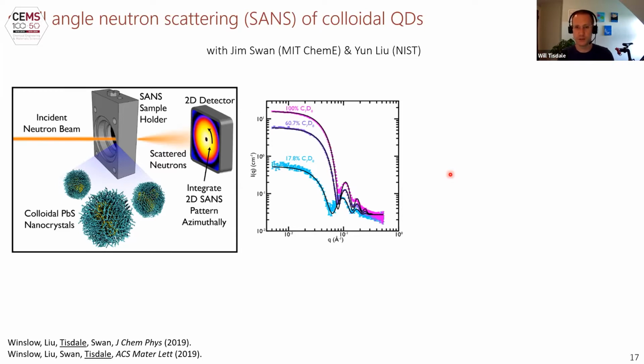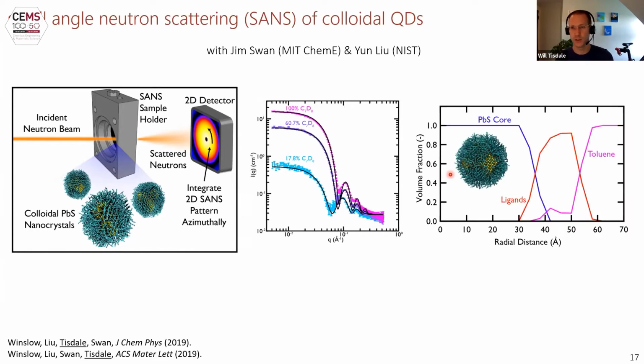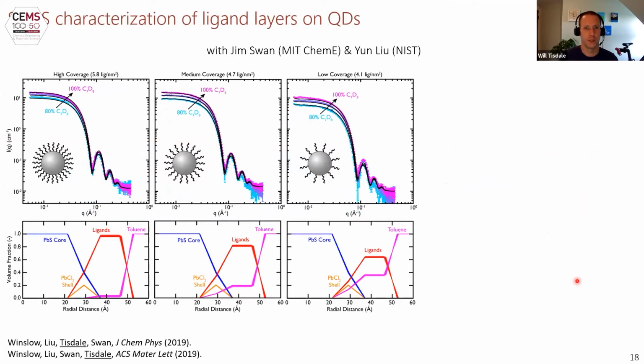And as we change the deuteration fraction, from the standpoint of the neutrons, the effective size from a neutron scattering cross-section standpoint is changing, even though chemically nothing is changing outside of the ligand shell. So Sam, our joint student, has developed MD-inspired models where we can determine the volume fraction of the material as a function of radial distance and allow us to access things like the density of ligands on the surface and the penetration of the solvent into that ligand layer. So here's some example experiments we did where we took the same size batch of nanocrystals and varied the ligand coverage on the surface, as measured by proton NMR spectroscopy, and then did the neutron scattering analysis.